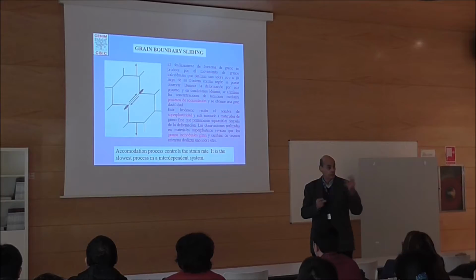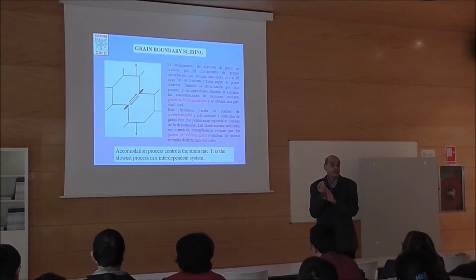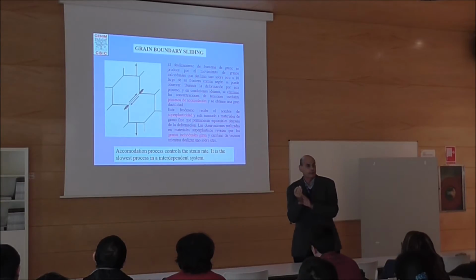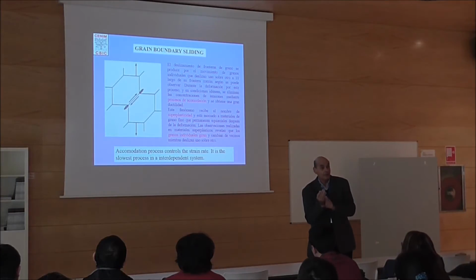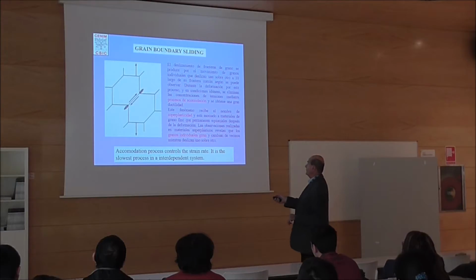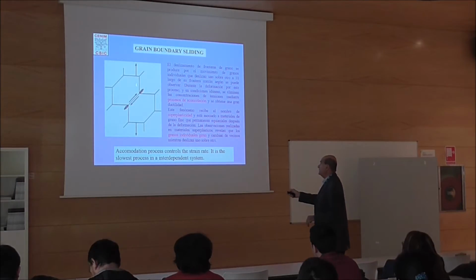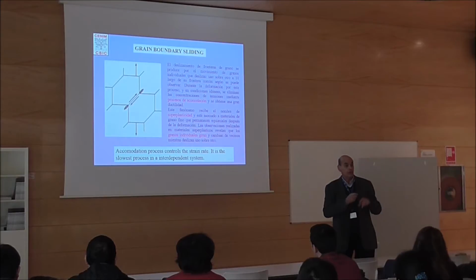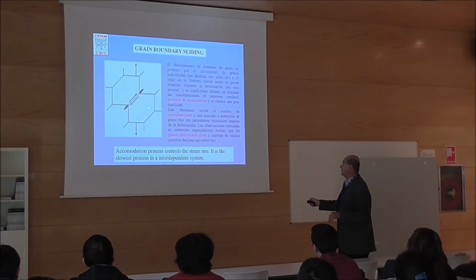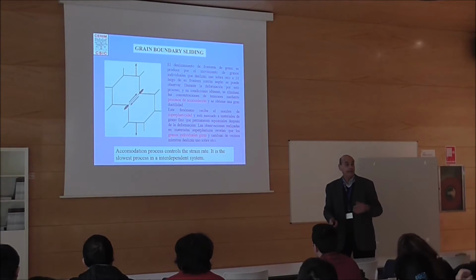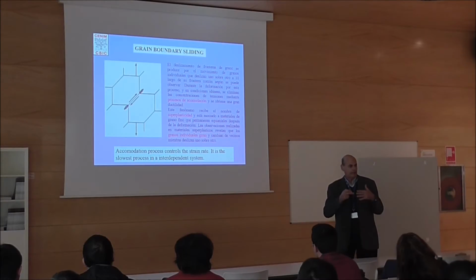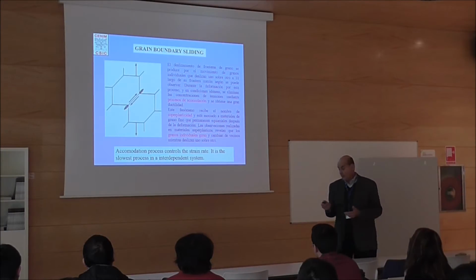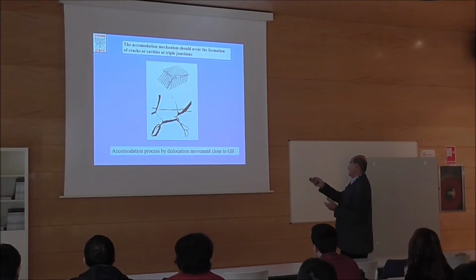So we have two processes again. Grain boundary sliding is likely very fast, and then we have a slower process that is very difficult to demonstrate. Probably slip, creep, climb of dislocations, but close to the boundaries. Nothing to do with a slip in a given system that we just saw. It is just along these grain boundaries that gives the n equal to 2. But this is empirical. We cannot demonstrate it. Nobody has demonstrated it. We think that this is the way. And this is okay.